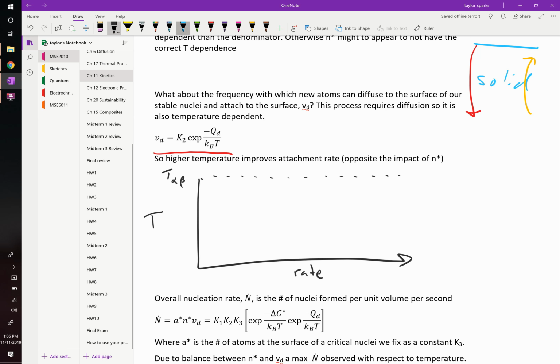We have two different effects in competition here. You've got this thing, N star, which you get more and more of the lower and lower you go. So the rate would be increasing based off of N star. There's more critical nuclei. But your rate of attachment is going to be better and better the higher you go. So V sub D is going to be up there. And the total transformation is both of these put together, right? So when we put them together, the overall transformation might look something like that, okay? That doesn't yet account for growth, but that's critical nuclei and attachments, okay?